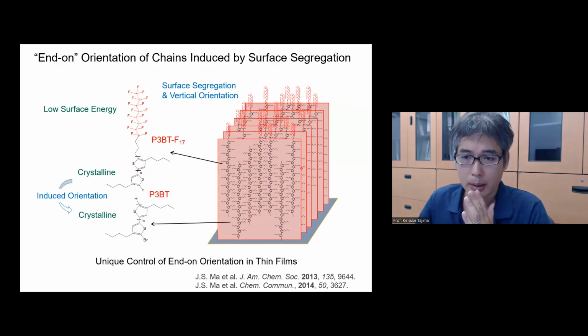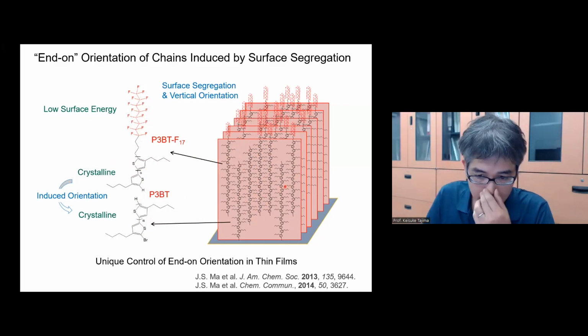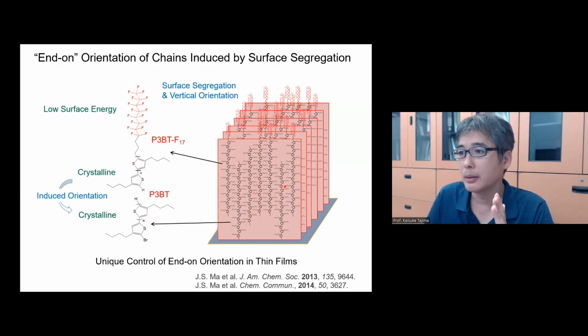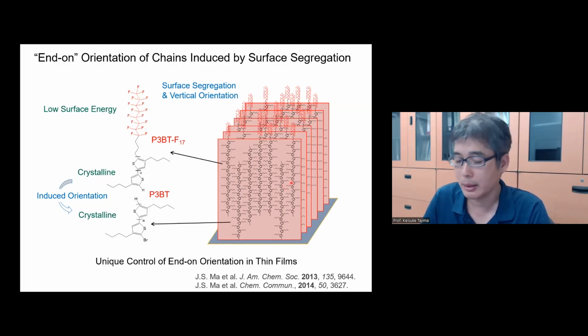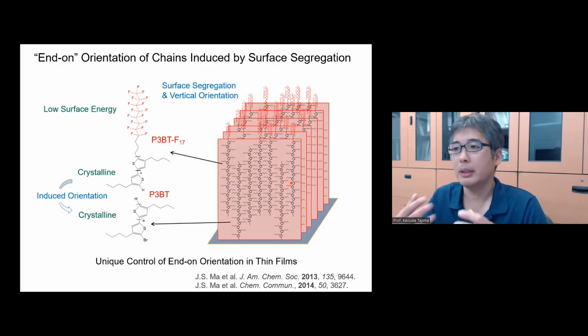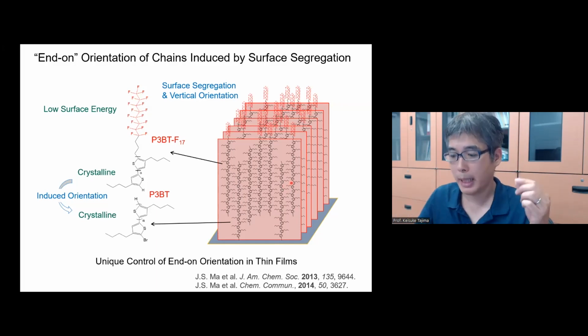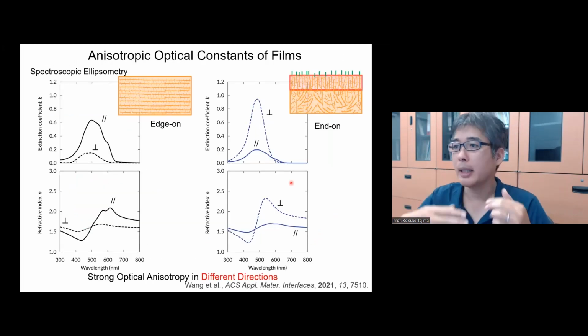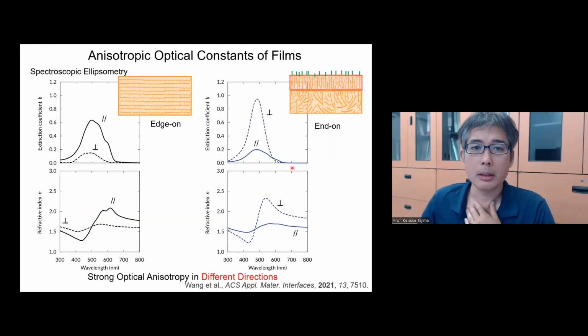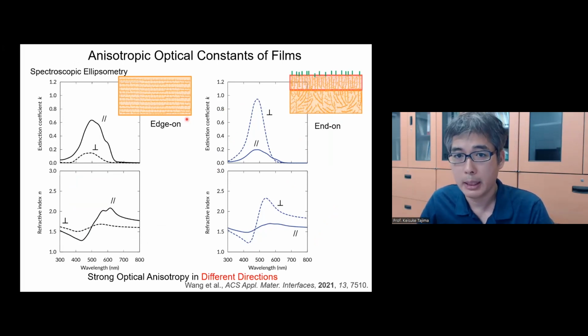So it's kind of orientation control from the surface, and it's kind of unique. You cannot find many examples of this end-on orientation in polymer films, because usually, if you can imagine, the long chain tends to have the lying-down orientation. So what happens in this film is that we can see several property changes.